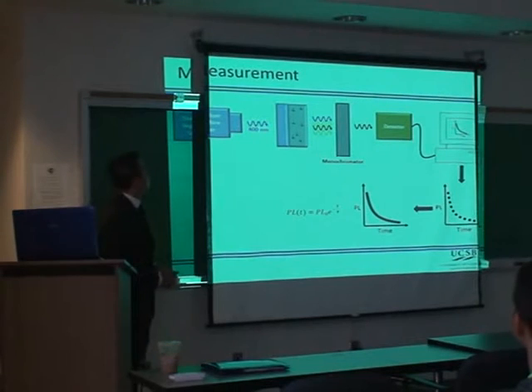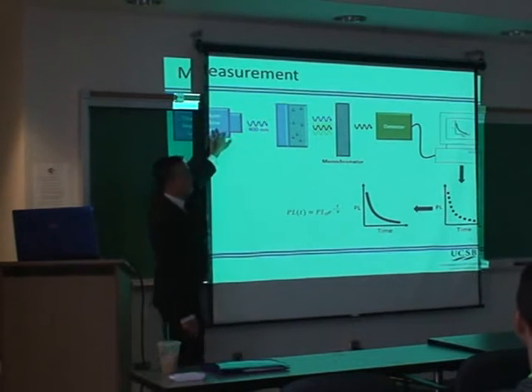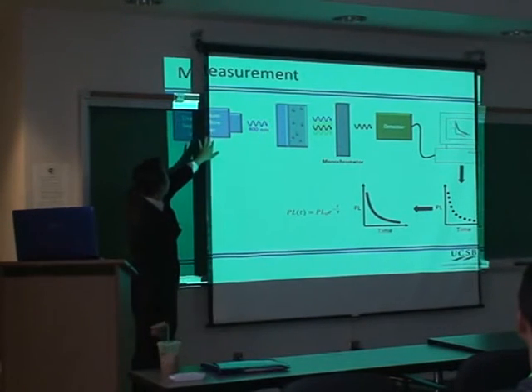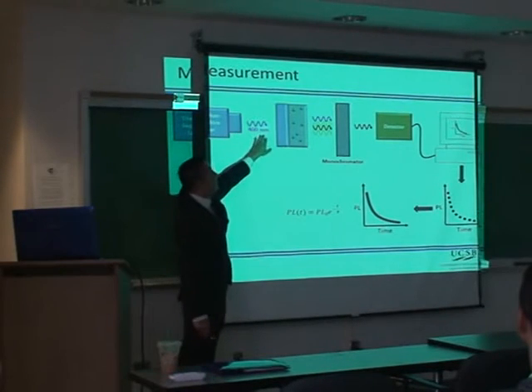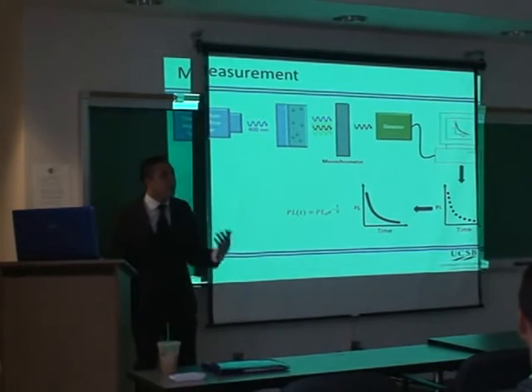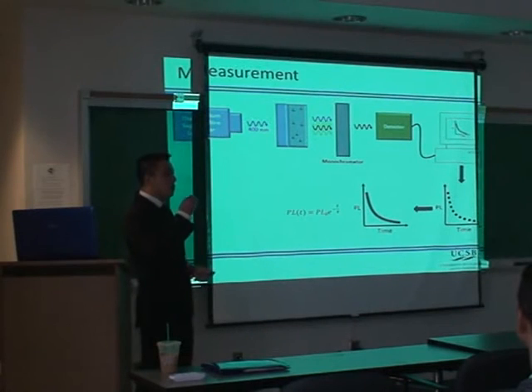The next thing we do is we do our measurement. And this time we have a different type of laser. We have a titanium sapphire laser that emits at 400 nanometers. The main difference between the other lasers is that this one emits a very short pulse. It kind of pulses the film.